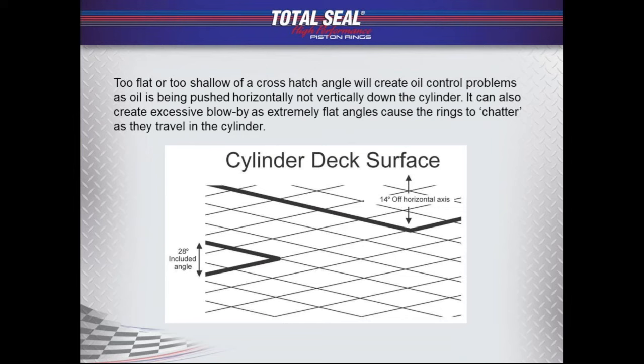Some of your flat engines, Subarus, Porsches, some of those will run a more vertical crosshatch angle, but not because they're trying to get the oil up to the top of the cylinder. They're trying to get the oil back into the sump, making it an easier pathway for the oil to move. As we flatten the crosshatch angle out, the oil wants to move side to side, not up and down. If we get too flat, into oil migration, we can get a chattering or stuttering effect as the ring is going over that. It starts to kind of lump up like driving over a railroad track. So too flat of a crosshatch angle can create a problem.